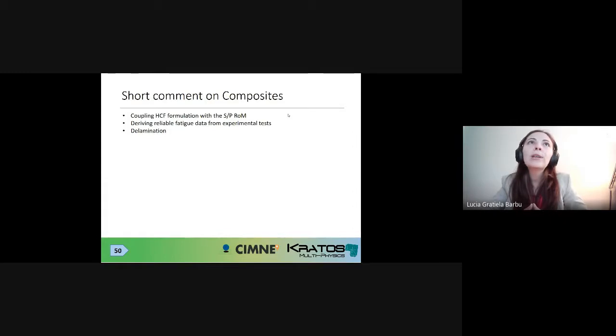Also, we've been dedicating effort to deriving reliable fatigue data from experimental tests. You'd think this is such a simple issue, but it's not, because it's very difficult to have SN curves, for instance, for the high cycle fatigue domain, for the fiber and for the matrix, in order to isolate well what the cyclic behavior of each component is, so that you have good control of the cyclic behavior of the composite. This is very complicated to do, and Barbara, our PhD student, has been working on how to collect this data. Also, delamination is a very important phenomenon for composite materials, and Ali has been dedicating effort to formulating a delamination model for composite materials.